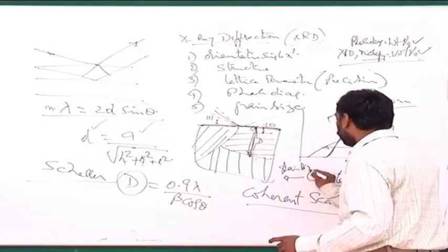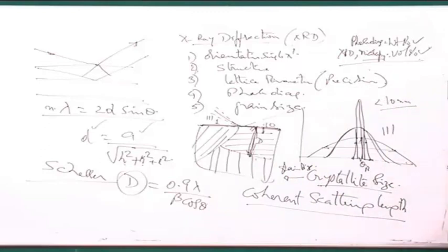But sometimes even inside a grain, there may be what are called subgrains. What you are actually seeing is then the subgrain size. Provided your grain does not have any subgrains, what it gives you is actually the grain size. So if you have a powder particle that is polycrystalline, you will not get the particle size here. You will only get the grains inside, and that average grain size is what you get. You are only getting an average, a bulk average technique. There may be a range of grain sizes, but you will not get the range.